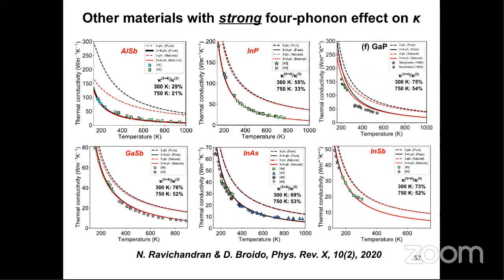So there are other materials also. Boron arsenide is not the only case where 4-phonon scattering is important. In fact, we have calculated the thermal conductivity, including 4-phonon scattering, for a broad range of materials spanning the entire III-V family. And we find that for a number of materials, 4-phonon scattering, that is beyond the conventional theory, is very important. As you can see in these pictures, the solid lines are my calculations in this new unified framework, and the dashed lines are the conventional picture. And the experiments are really lying on top of the curve without any adjustable parameters. So it's a very predictive scheme, which includes the reality of having higher order effects in thermal transport.